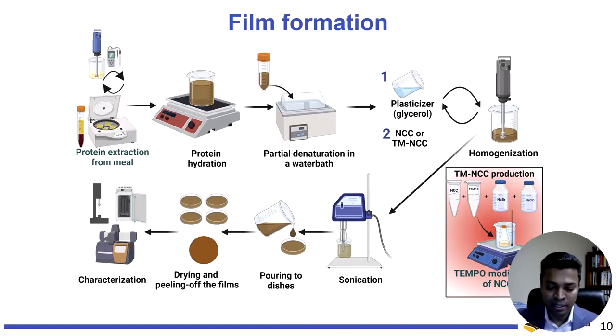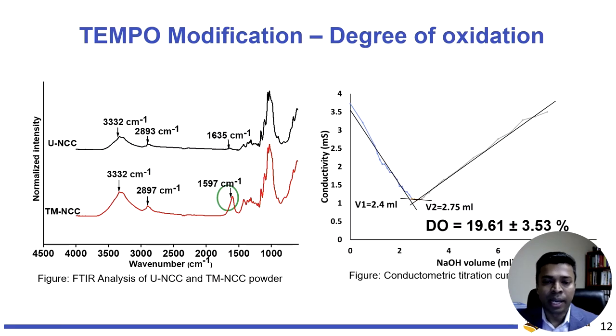Then we used the solvent casting method to create the films, and then took a look at the different parameters when it comes to the packaging materials. The first thing we wanted to measure is how appropriate our oxidation method is for this particular research. When we did the conductometric titration, we found out that we successfully managed to convert almost 20% of the hydroxyl groups present in the nanocellulose into carboxylic groups, which is a pretty good degree of conversion when we think about the properties that it will change. And then we used FTIR to confirm this TEMPO-mediated oxidation as well.